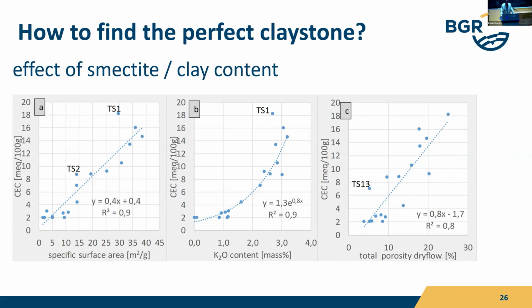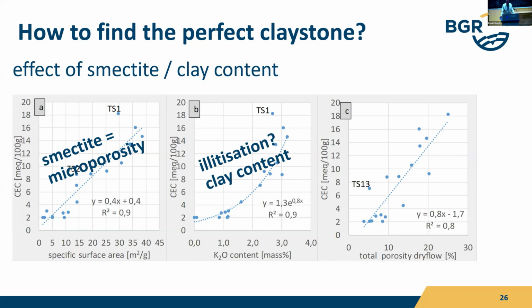Looking at clay data, we compare the specific surface area with the CEC, the potassium content, total porosity with the CEC, and these plots were not really surprising, since smectite is the main carrier of microporosity. In case of the potassium content, we think that we see more the clay content. If it would reflect illitization, then the shape of the curve should be different. And we can see that the porosity is obviously related also to the clay minerals, but this is published since decades, so there is nothing new. But it's always nice when you're investigating new sample sets to see that the data is consistent with what was published before, right?